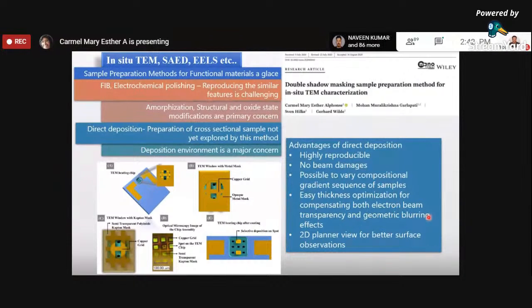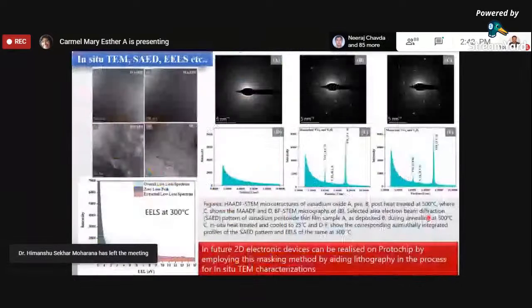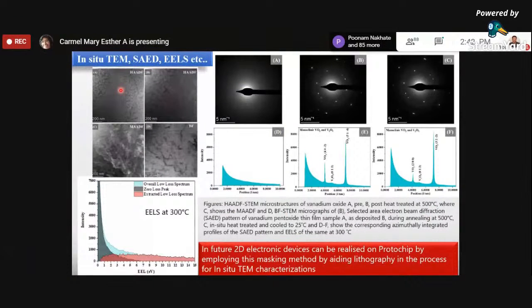We demonstrated this setup by doing one in situ study. This is the vanadium oxide thin film, coated directly on the Protochip by using this method. This is before heating, and this is after heating. Then we looked at selected area electron diffraction. First it is completely amorphous. During heating, at 500 degrees centigrade, we observed the formation of monoclinic VO2 and mild monoclinic V2O5 crystalline nature. Upon cooling, we observed the structure is in a stable condition.